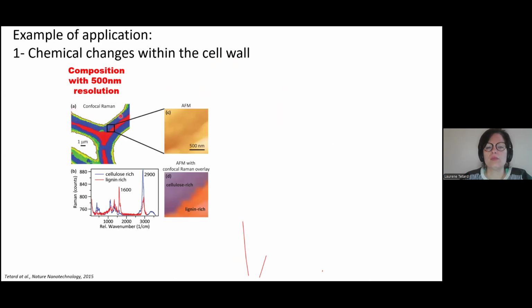we can map it with confocal Raman. So this is an optical measurement, kind of like a fluorescence measurement, but measuring the Raman signature of each pixel and reconstructing the plant cell wall composition. So we can see that there's a layer that is lignin rich here and that is more lignin poor, or cellulose is more prominent here.